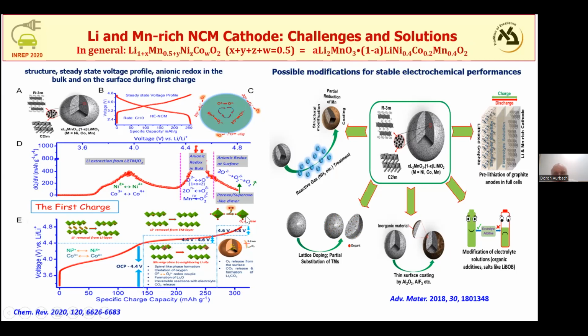We need high potential charging in order to activate this material, and what we activate, in fact, is that we allow the oxygen atoms, which are -2, to also undergo redox activity, and this redox activity of the oxygens is the source for the high capacity. So the key issue in order to stabilize this material: if you turn oxides to peroxide, the oxygen becomes very reactive with the electrolyte solution. So the key issue is coating. We have to coat the material with buffer zones, and we can do it through solution chemistry, by ALD processes, or by gas treatment. The idea is to form a good buffer zone on the surface, avoid any contact between oxygen and the electrolyte solution, and also avoid the release of oxygen due to oxidation of the oxides in the material.